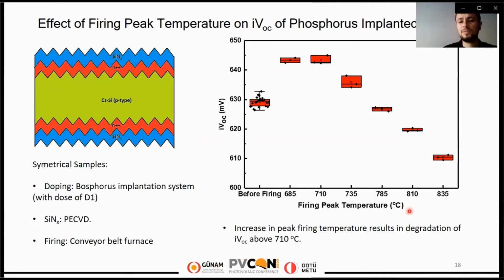The output of this experiment was very interesting because the typical firing temperatures, between 750 and 800, are very detrimental to the implanted emitter. But when you decrease the firing temperature, the implied VOC is improving for the implanted emitter.